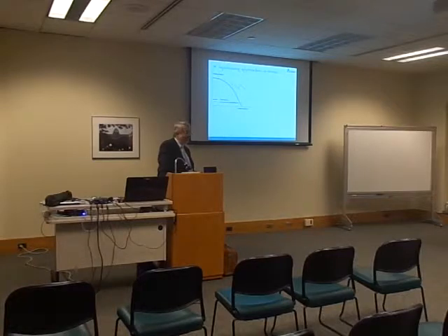Okay, and then my second question was kind of going back to what these two asked about the diffusion rate. And in your laboratory experiment, you were just using the aged binder and the rejuvenator, correct? Yeah. And at what temperature was that? Several, because of what we said. I can't remember what I showed, but we have to do it at more than one because it's a molecular process. So I think it was 180 for 30 minutes, the one I showed.